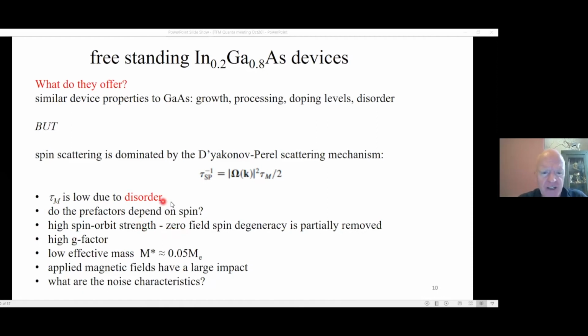InGaAs has a very high spin-orbit coupling strength, so the spin degeneracy is partially removed at zero field. We don't need an external field. It's got a high g-factor. If we were to apply a magnetic field, the spin energies are large through the Zeeman effect. It's also got a low effective mass, so applied perpendicular magnetic fields have a much larger effect on the localization properties. And also, perhaps the noise characteristics might be different in this system.